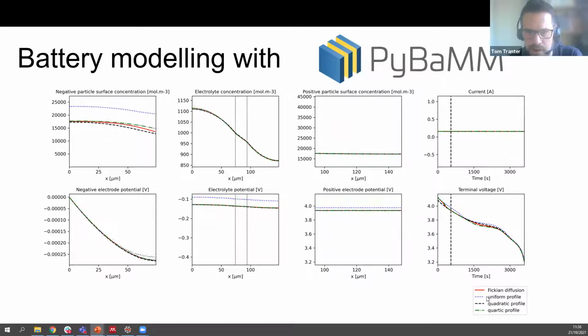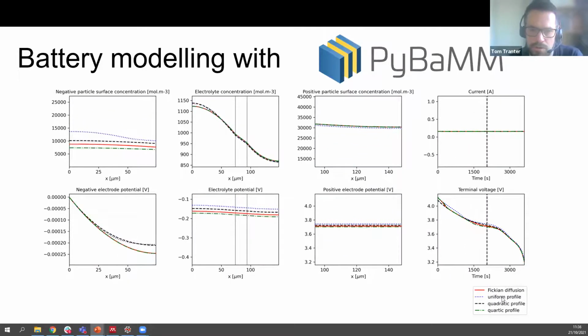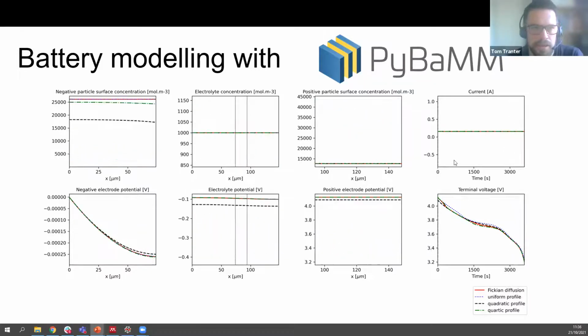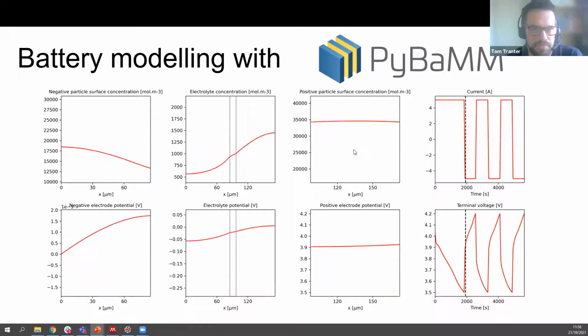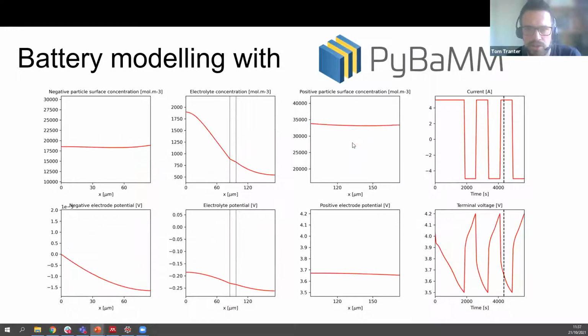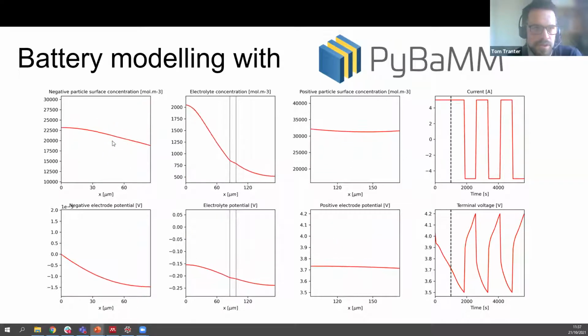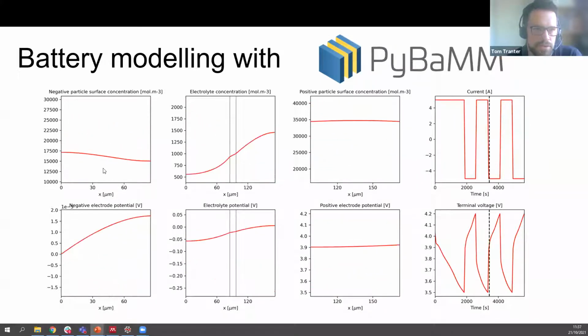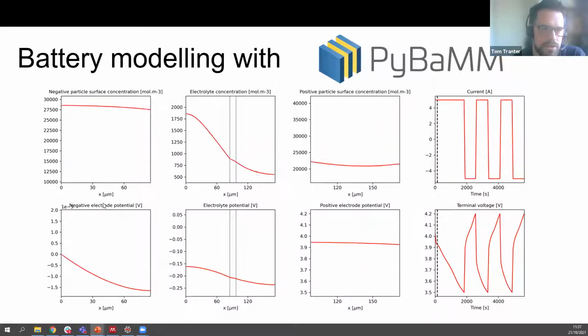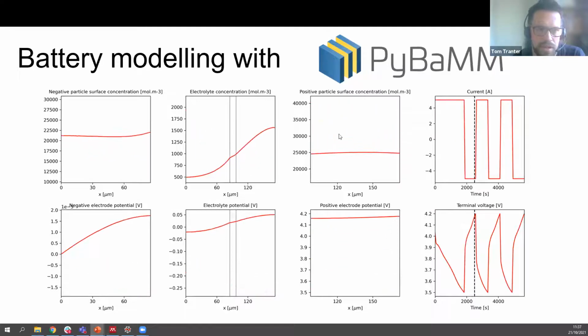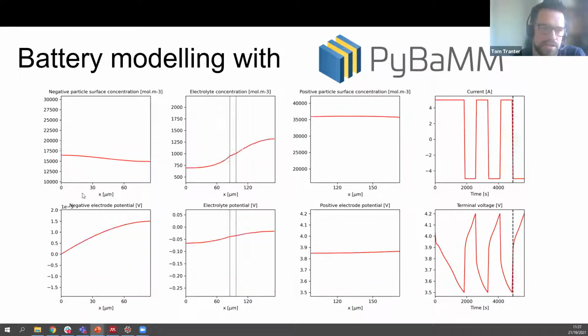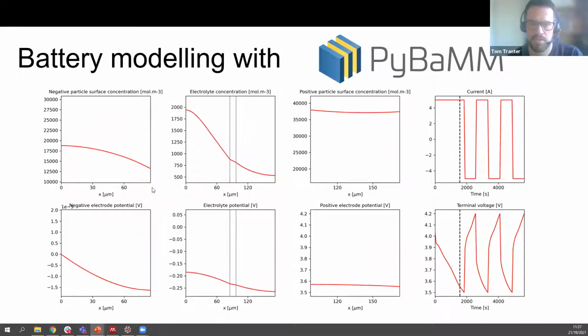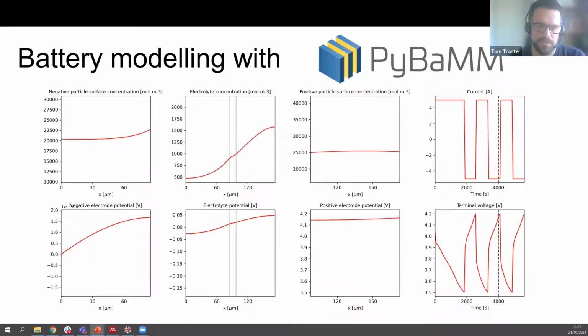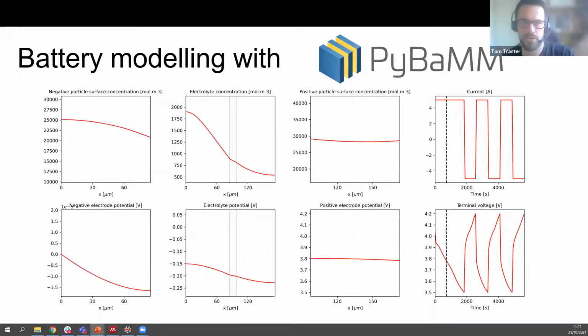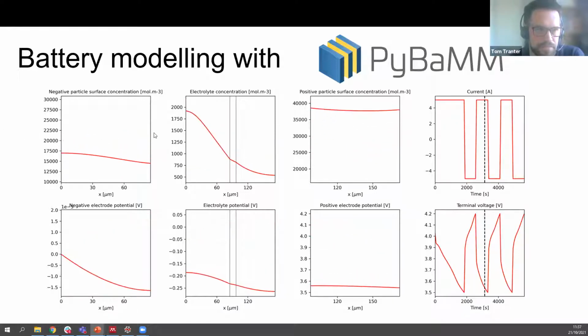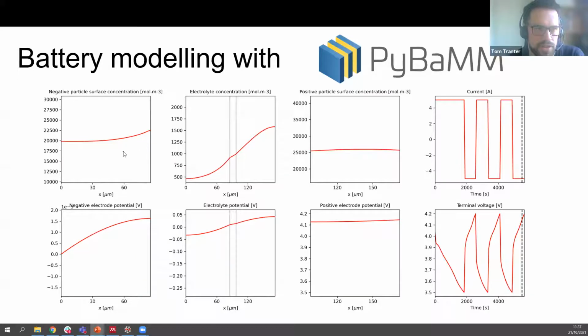This is actually comparing a different particle level model of intercalation. This one is cycling the battery, just constant current, charge and discharge at a fixed current of 5 amps. And you can see the two things that are probably most important for us studying the battery with acoustics are these negative particle concentrations and positive particle concentration as they go up and down. And this on the x-axis is, if you imagine drawing a line between the center of the anode and the center of the cathode, that distance there as you go through the cell, through the separator. And these are lithium concentrations as they intercalate.